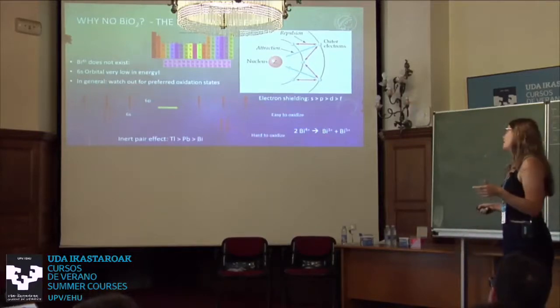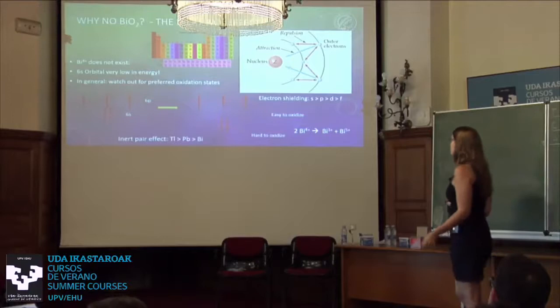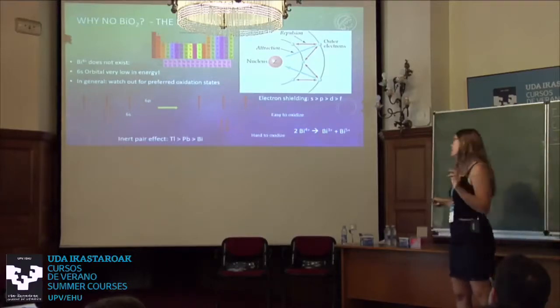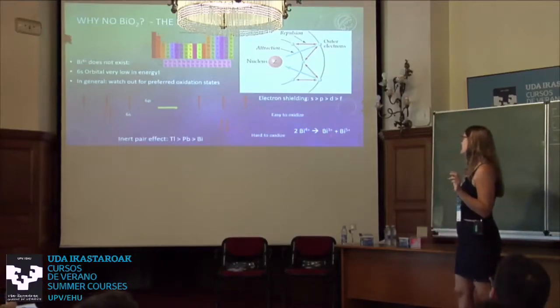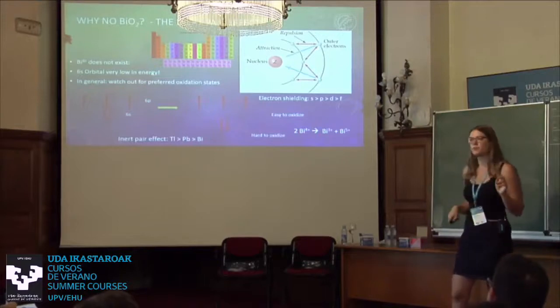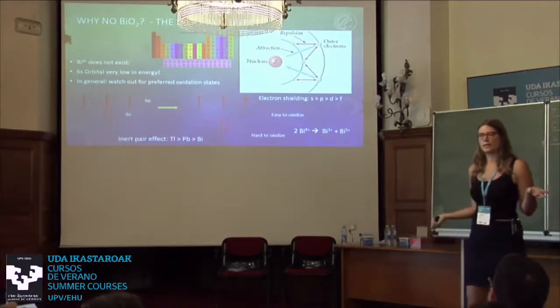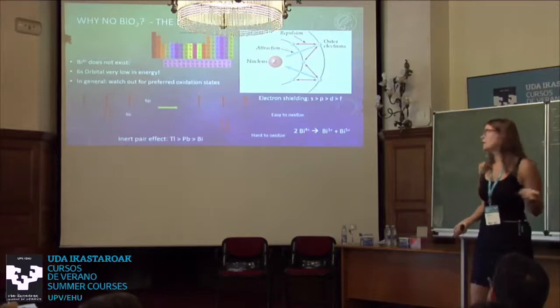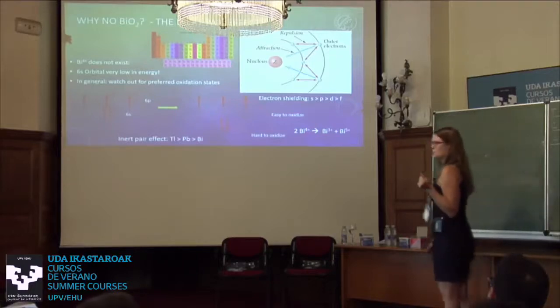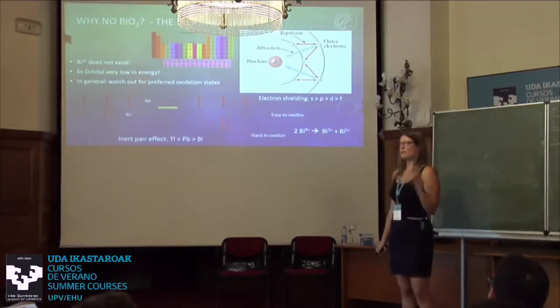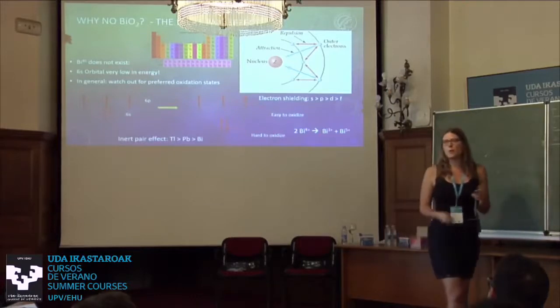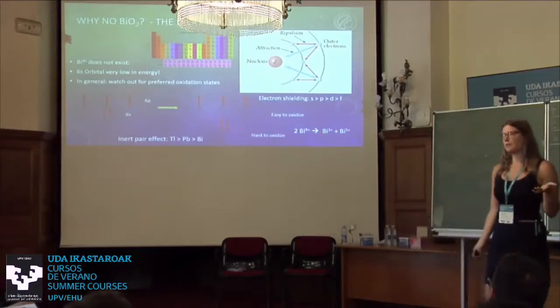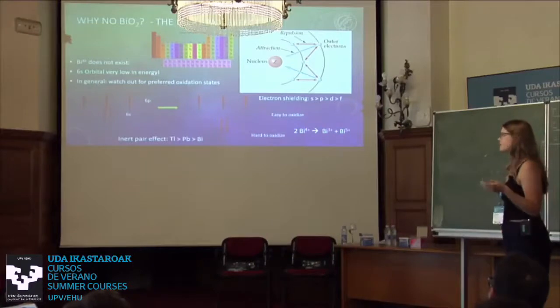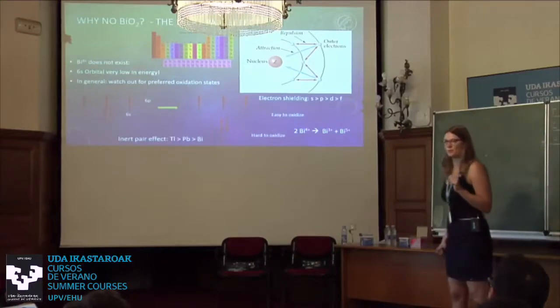Okay, then if you have a 4 plus bismuth formally, it often separates into 3 plus and 5 plus because it doesn't like to have just 1 electron in there. And so there's no known example of a bismuth 4 plus compound. So if you actually could make BiO2 with bismuth 4 plus and bismuth in the oxygen tetrahedra, much more than having a new semi-metal, you might get a really fancy prize in chemistry for establishing those rules. Okay.